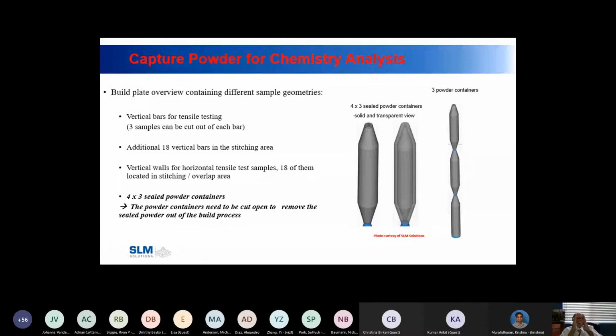So when you get powder, you take 100 grams, you send it out to an outside lab, and you validate the chemistry of that powder is identical to the material data sheet. You don't want to start if it's not identical, right? And then you start printing, and you capture powder at the bottom, and you capture powder at the middle, and then at the top. So what you do here is that you send these powder specimens out to the exact same lab, or a different lab if you wanted, and you measure the chemistry as it goes up in the build. You also take at least one specimen and measure the chemistry of the printed part. And what you want to know is, does the printed specimen chemistry change during the printing process? That's one build, and that's very expensive to do, but it has to be done.